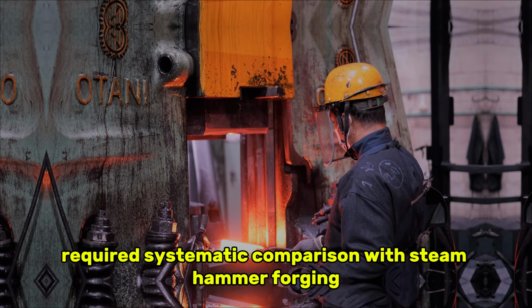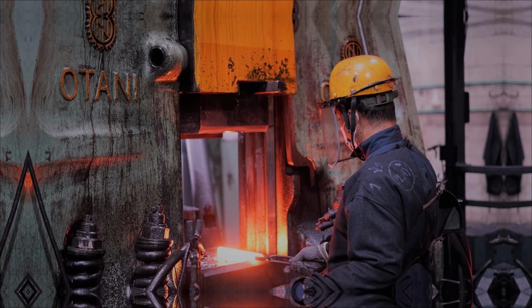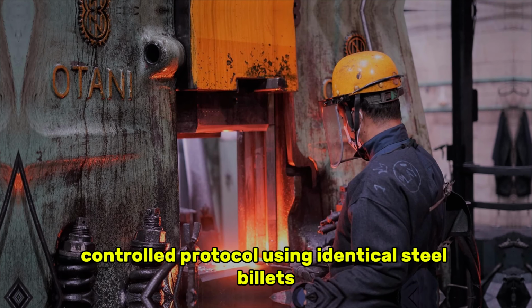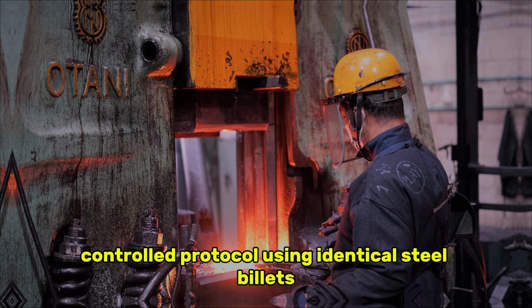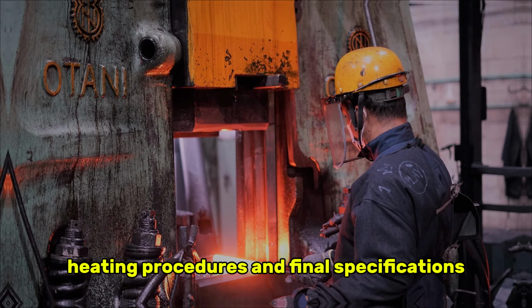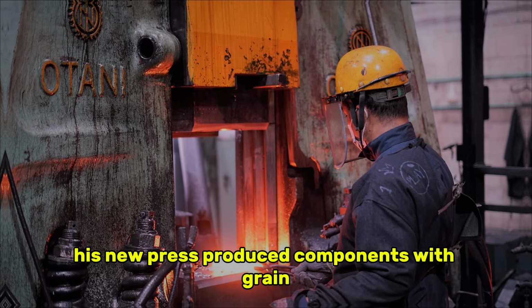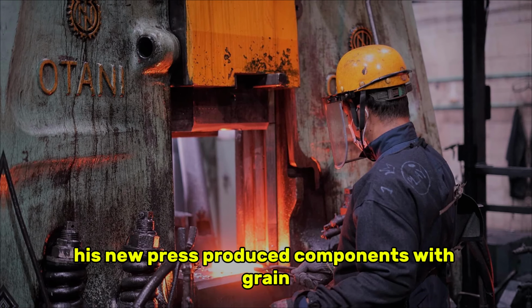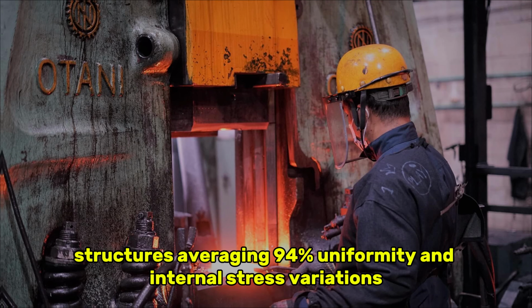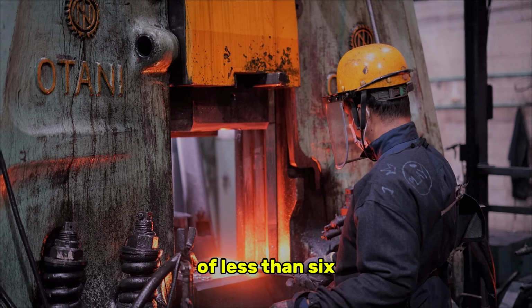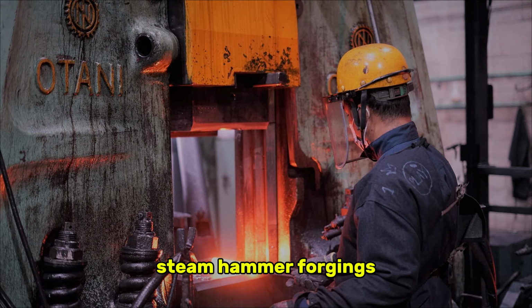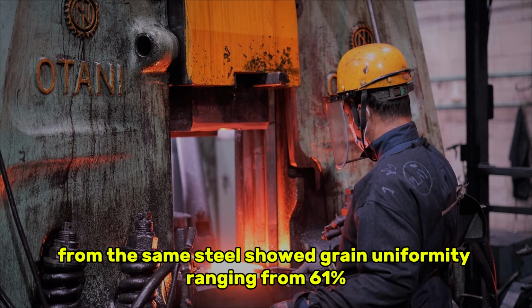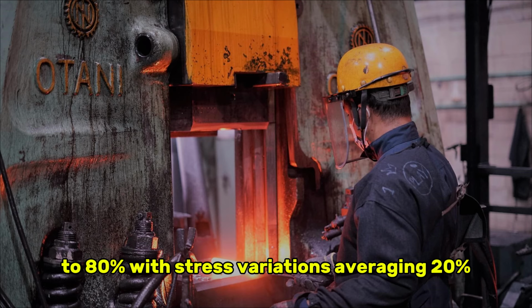Testing the redesigned press required systematic comparison with steam hammer forging. Hartwell established a controlled protocol using identical steel billets, heating procedures, and final specifications. His new press produced components with grain structures averaging 94% uniformity and internal stress variations of less than 6%. Steam hammer forgings from the same steel showed grain uniformity ranging from 61% to 80%, with stress variations averaging 20%.